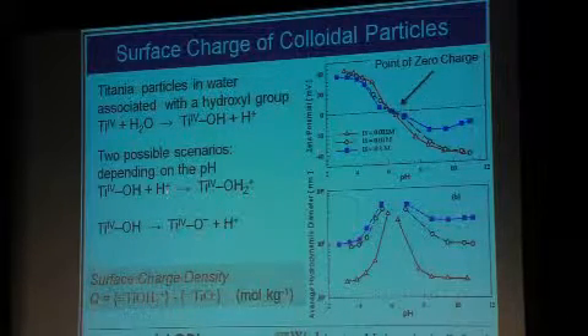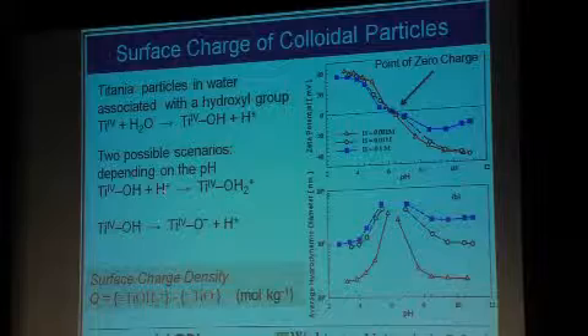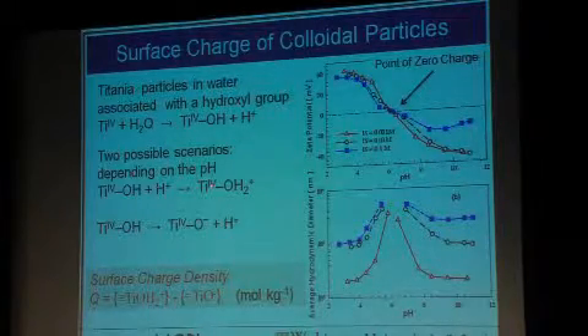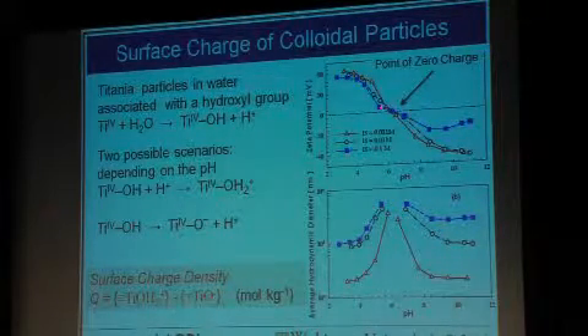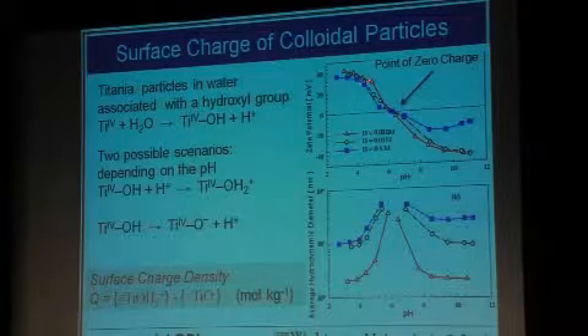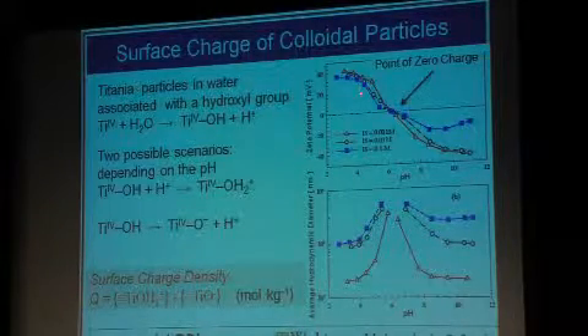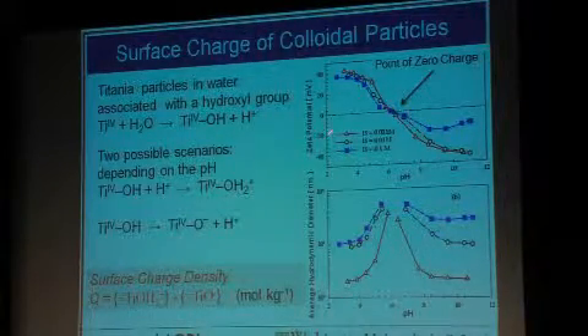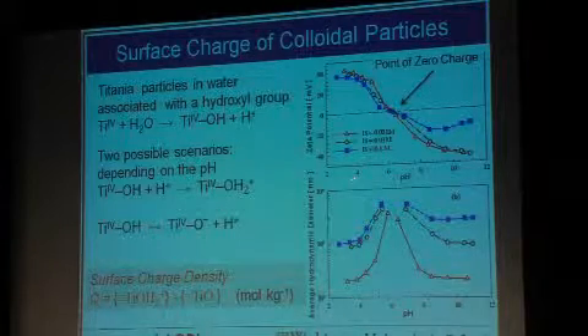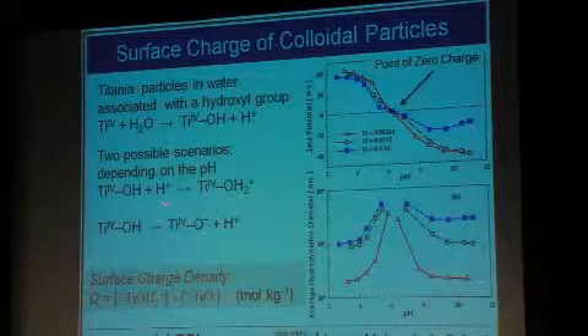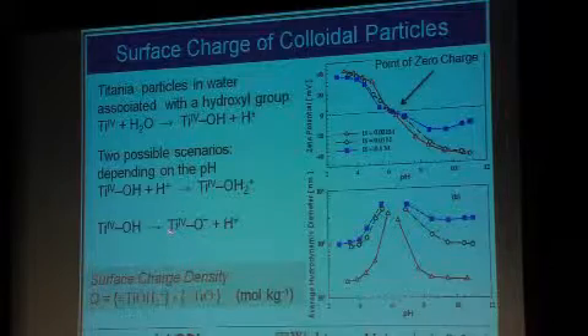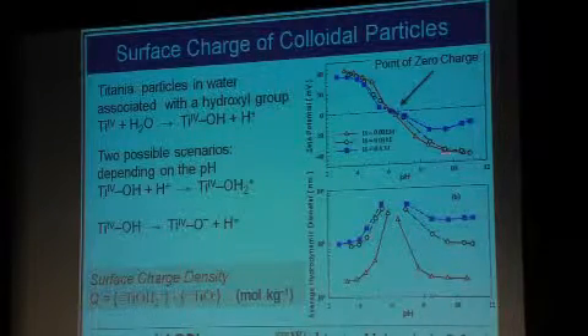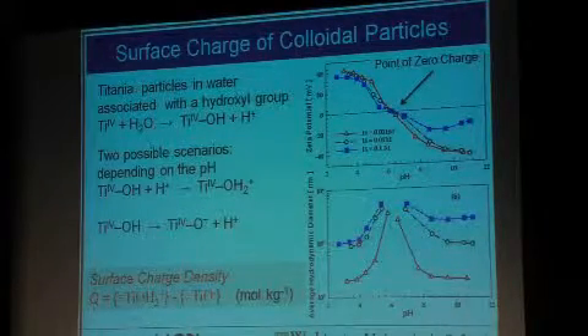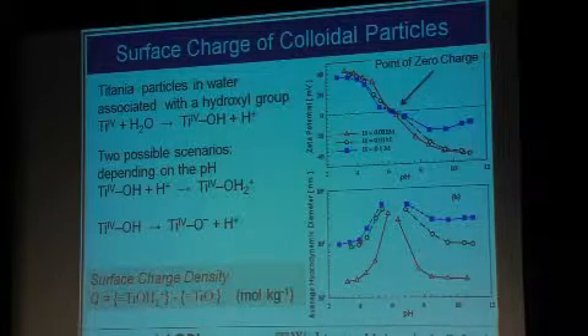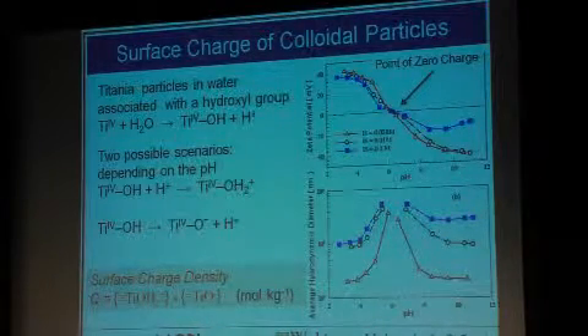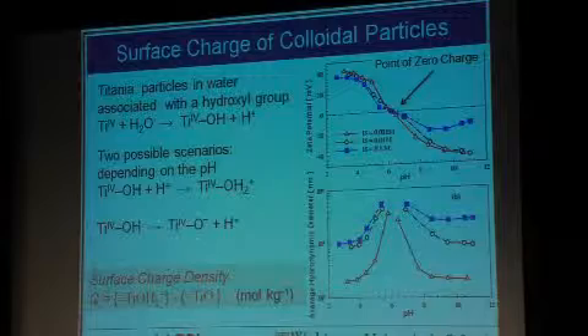So if I have a low pH, which means a large amount of hydrogen ions, this is a preferred product. And at low pH, I'm going to have a positively charged TiO2 nanoparticle. Zeta potential is positive. If I have a high pH, low hydrogen ion concentration, the reverse, this is promoted, and I have a negatively charged material. So the same TiO2 particle, depending on the suspension conditions, could either be positively charged or negatively charged.